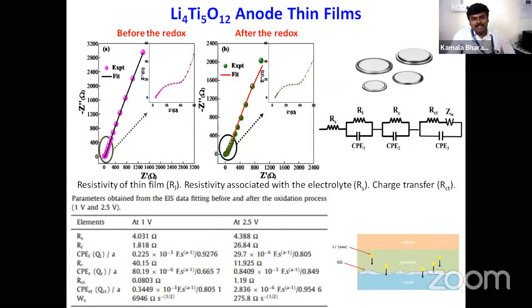In addition to that, we were interested to study the lithium ion dynamics when we charge and discharge. In order to study the dynamics of lithium ion, we have carried out the impedance before the redox and after the redox. So this shows the impedance curve of the lithium titanate before the redox, and this is the impedance curve of this thin film after the redox. And we fit these curves using equivalent circuit.